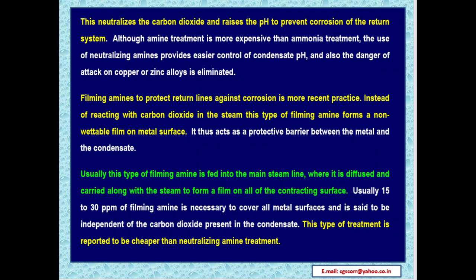Filming amines to protect return lines against corrosion are a more recent practice. Instead of reacting with the carbon dioxide in the steam, this type of filming amine forms a non-wettable film on metal surfaces. It thus acts as a protective barrier between the metal and the condensate. Usually, this type of filming amine is fed into the main steam line where it is diffused and carried along with the steam to form a film on all of the contacting surfaces.